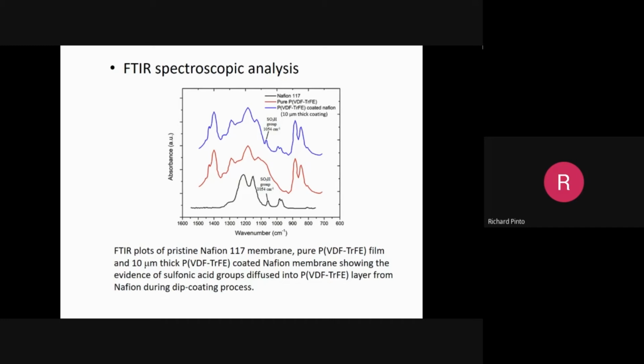Otherwise, there are no sulfonic acid groups in pure PVDF-TrFE, and you see sulfonic groups in the coated membrane. And the base membrane has the groups which are responsible for H plus mobility by hopping conduction. So this is the important finding.